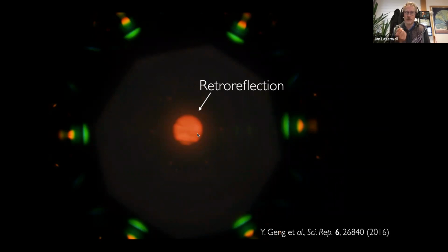So that's retroreflection. The light comes along the helix. The helix reflects the light back, and it's with the longest wavelength, which in this case is red. Then you see outside the illuminated area, there are green reflections and eventually red-orange reflections in a hexagonal pattern. And to understand where they come from, we open the aperture. So right now we have the smallest aperture and we have only this part illuminated.